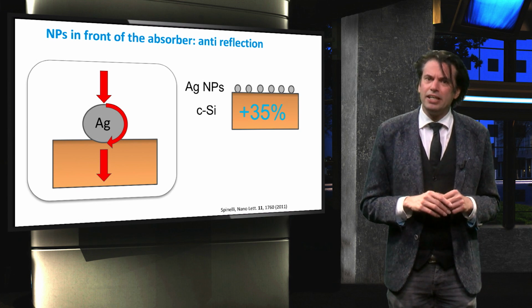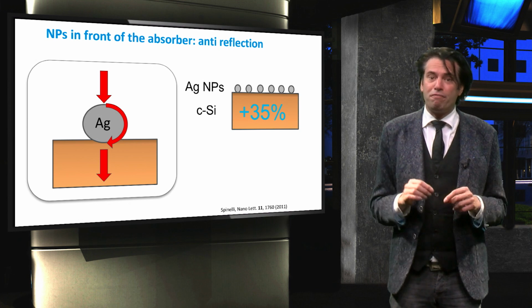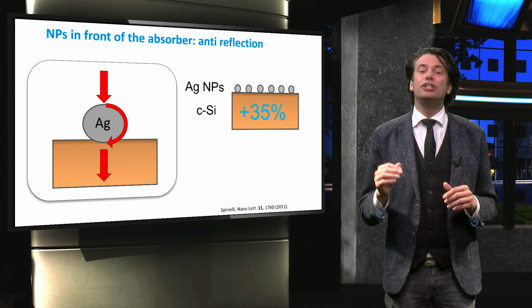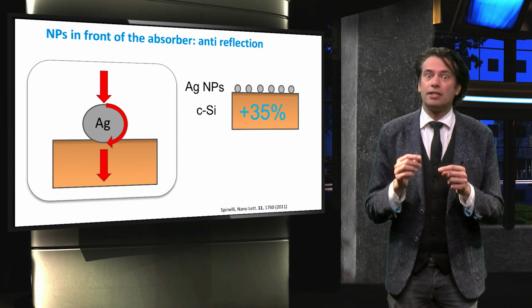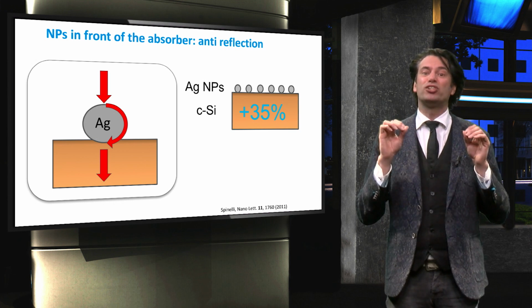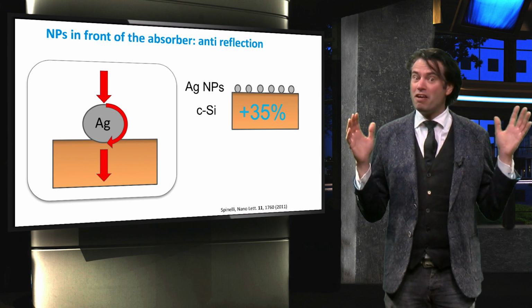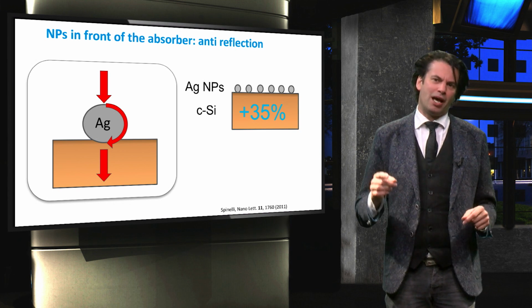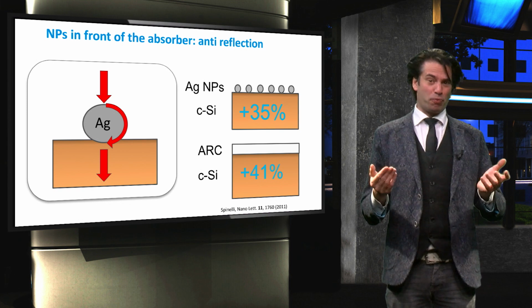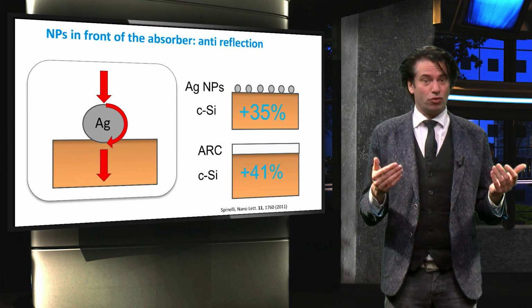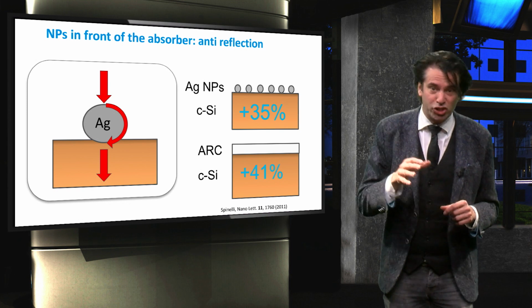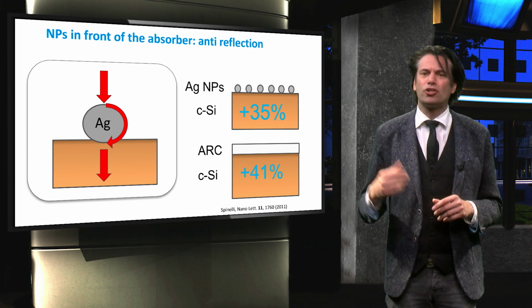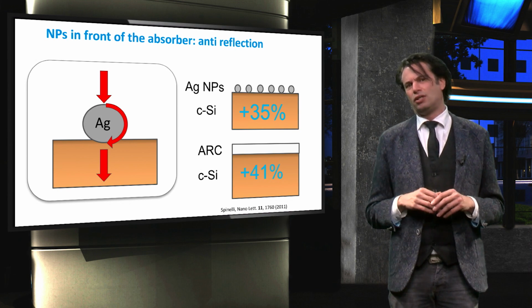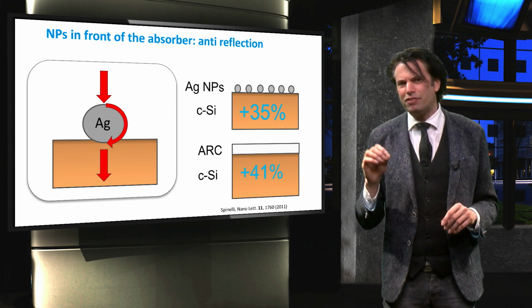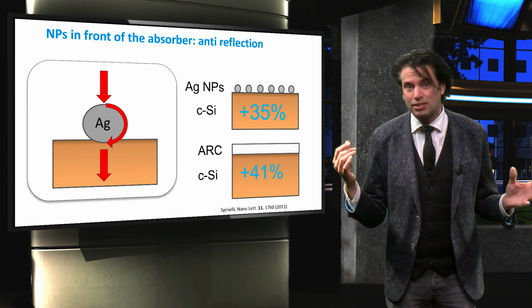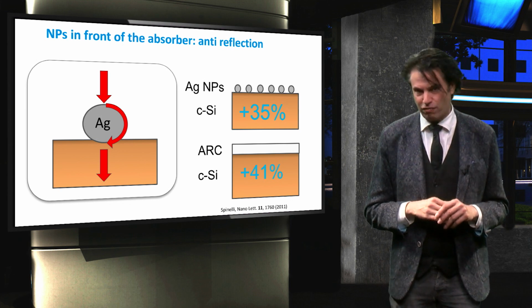Spinelli systematically varied all the parameters and found that in the best case, the absorption in crystalline silicon is enhanced by 35%. This seems to be very promising. However, the conventional approach of using an anti-reflective coating of silicon nitride, which is much cheaper and simpler, enhances the current by 41%. So it's unlikely that silver nanoparticles will in practice be used for their anti-reflective properties.